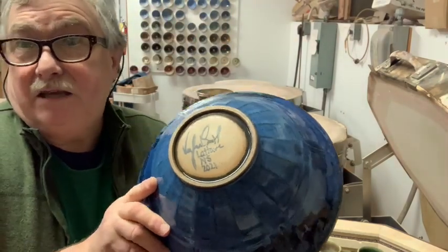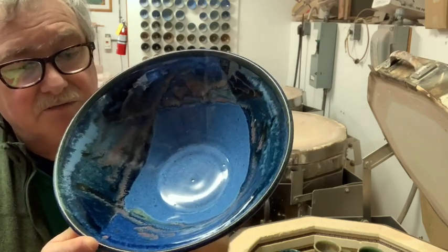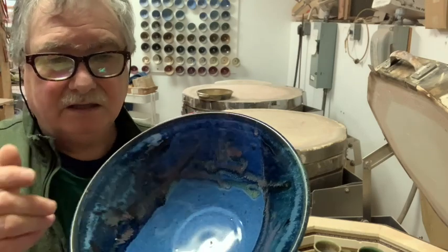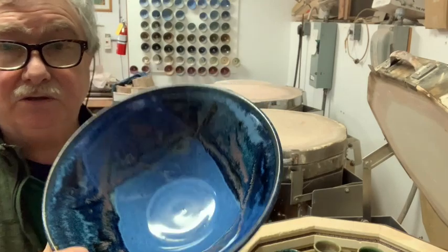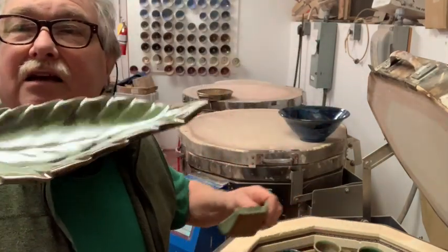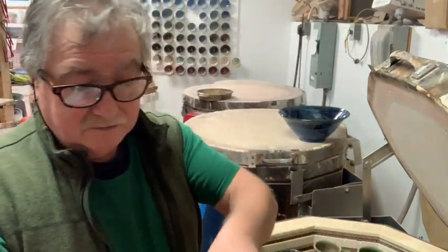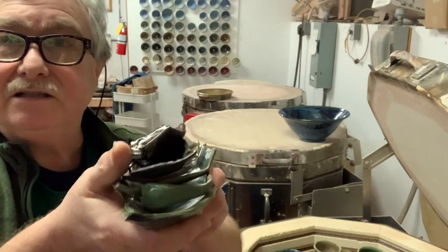It really does make a nice color - and it's just luck, what I'm making at that time during the recycle. It's got the bright blue from Mastering Cone 6 Glazes, but my own dark blue is over the top, and then I've got oatmeal there as well. Dark blue is when you add a little bit more cobalt oxide than they say - if you say 1% that's that blue, and I think if you want to get darker, you'd add like 2% or 3% cobalt oxide, which is very powerful and you get a darker blue. My wife makes these little trays for kiln fillers - we just throw these in. Generally speaking, these will pay for the firing. If you've got enough of these little things squeezed in, you can actually pay the electric bill for the firing.